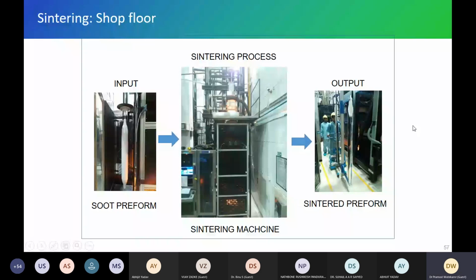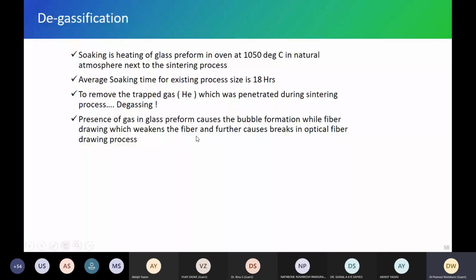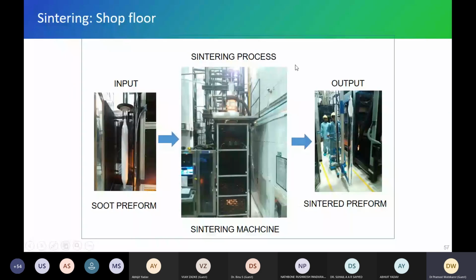And we also need to do degasification, because what happens is that we always use helium. This is a soot, right? Soot is going to be converted into glass. There is a huge possibility that some gas is trapped inside. This soot means there are a lot of pores. So if some gas is trapped and you consolidate it to glass, because of high temperature that trapped gas can expand and form a bubble that can break your fiber and break your preform, or nothing happens, then it will make your fiber very thin. Very weak. So that's the disadvantage.